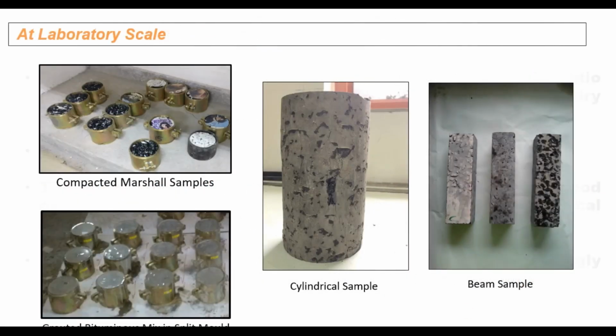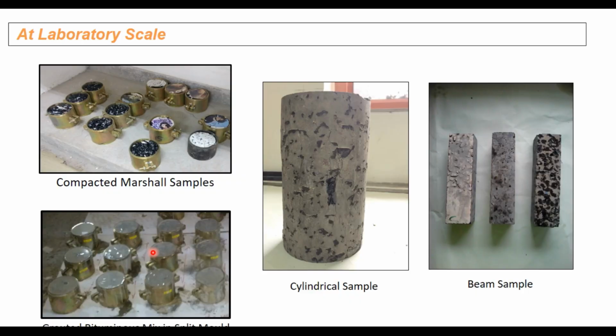Various engineering properties of CGBM like Marshall stability, compressive strength, ITS, and flexural strength are to be determined in the laboratory before recommending it for field production. So you need to determine the Marshall stability of the Marshall specimen after grouting of the specimen and proper curing. These are the grouted bituminous mix in the split mode, and they are cylindrical specimens. You can see here the grout has gone up to the full depth. Similarly, beam specimens. This one is partially grouted, and this is a fully grouted beam.